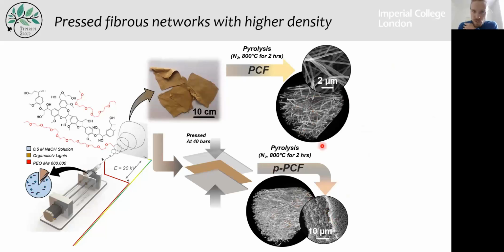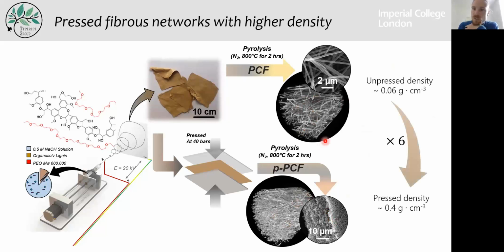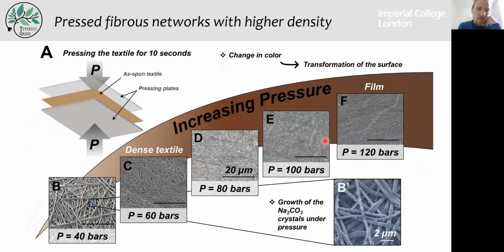Those are the X-ray tomography. And we managed to increase the density of these mats by 6 approximately. That is showing you basically when we press the mat at different pressures that we can merge these fibers into a film. So that's not really what we want to do. So that's why we chose 40 bars, because it seems like a good compromise between the dense mats where we can retain this fibrous morphology. And you can see also the growth of these crystals here on the surface of the fibers while pressing.